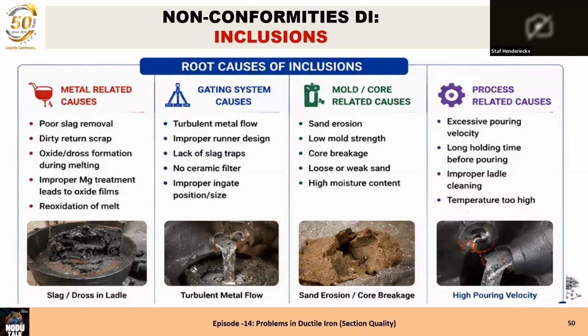Loose or weak sands. And the loose sand, I am sure that quite some molds are closed without looking if the sand was removed completely. And many foundries do not have a sufficient system for removing the last loose sand out of the bottom mold, the drag mold, before putting the cope mold on top of it. A high moisture content is always negative, because moisture is heating up and it's increasing its volume, and it will destroy the sand or the cores, whatever, the surface mainly, and then sand can break out.